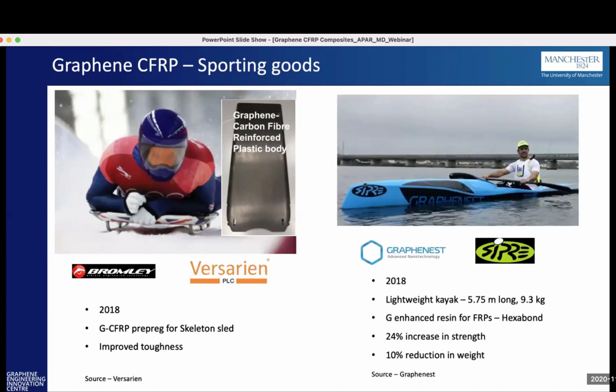So this, at the time we got this, was said to be the lightest kayak of its class in the world. I don't know how true that is anymore. I'd say it's back in 2018. But what these guys did, they added graphene to a resin system, called Hexabond, and then made a prepreg material with that. And what they found was a 24% increase in strength, which then enabled them to reduce the amount of material which was used. So they managed to save a total of 10% reduction in weight. And again, over something that size, a 10% reduction in weight is quite significant. So it's a really good test of graphene there.